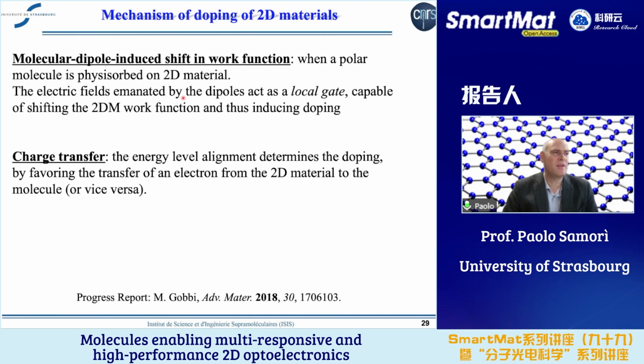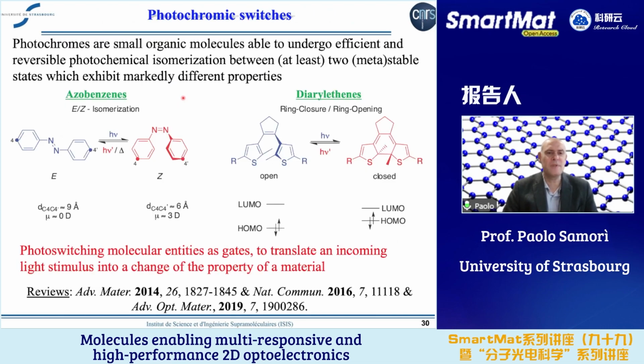The first one is the molecular dipole-induced shift of the work function that you obtain when you take a polar molecule and you physisorb this on the basal plane of 2D materials. And so the dipole of the molecule emanates an electric field, and this behaves like a local gate that is capable of shifting the work function of the 2D material, and this induces a doping effect. Now, to do that, we use photochromic molecules that are small organic molecules that undergo isomerization between different states,